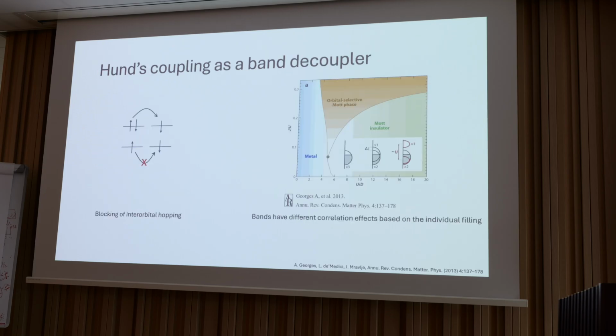And notably, one of the big consequences of this is it acts as a band decoupler. It blocks these interorbital fluctuations, so you can't gain in delocalization energy for J greater than 0 by hopping between orbitals. And so what that means is that these bands can have very different correlation effects based on the individual filling.